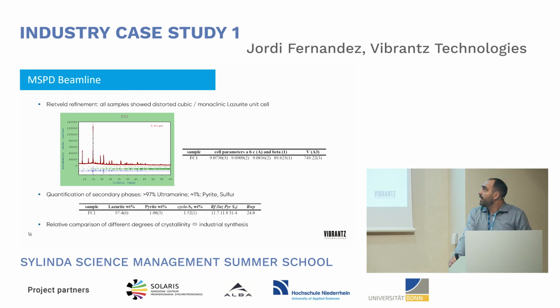In the MSPD beamline, we do refinement of all the samples that we send to ALBA. All of them show the distorted cubic sodalite unit cell, distorted to monoclinic. We have the different cell parameters, and we also did the quantification of the secondary phases. The pigments we produce are all around 97 to 98% ultramarine, and the secondary phases are pyrite and sulfur, around 1%. So we could have different compositional structures, and we compare the quality of the pigments with the presence or absence of the secondary phases and the cell parameters of the ultramarines.